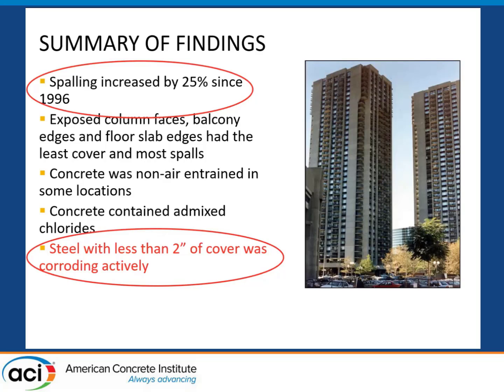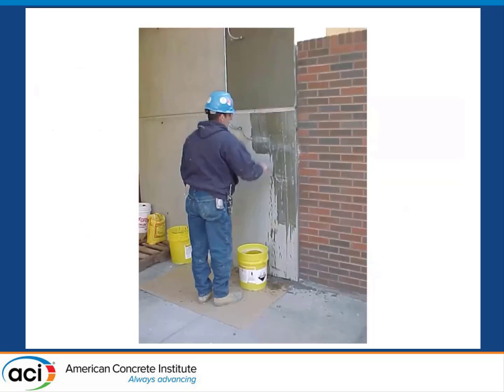So knowing this, the engineer had an idea of what they wanted to do, and they were considering obviously protective coatings and things like that. And they commenced with a mock-up. And as part of that mock-up, they picked two areas that were fairly easily accessible, and they did corrosion rate monitoring. So they embedded probes into the panels, and in one panel they applied just a coating, and on the other panel, they applied an inhibitor, a surface applied corrosion inhibitor, followed by a coating. And really, the engineer was trying to determine what was maybe the best approach given the conditions on site.